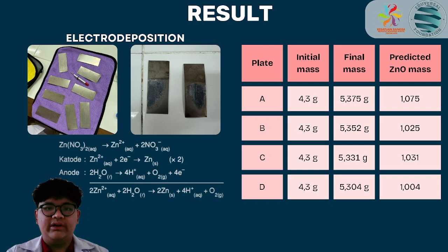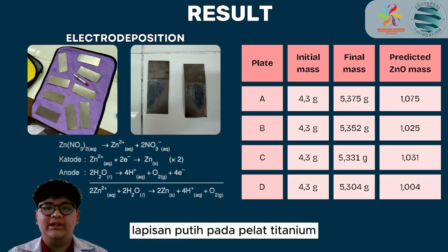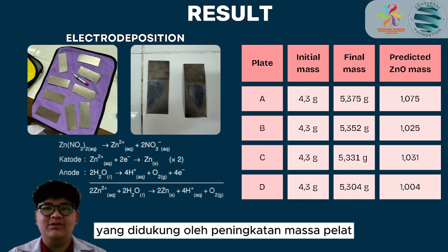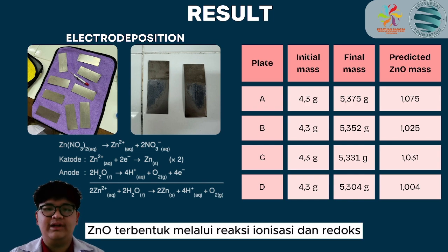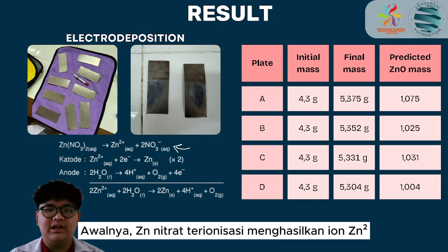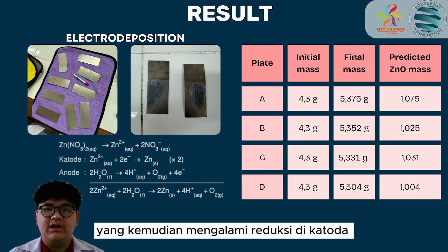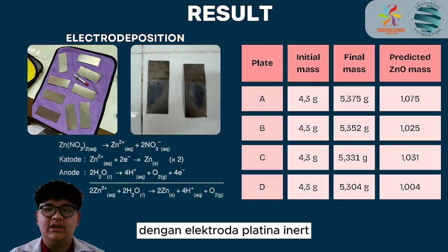Now the result. After electrodeposition, a white layer on the titanium plate indicates zinc oxide formation, supported by the increase in plate mass. Zinc oxide forms via ionization and redox reaction. Initially, zinc nitrate ionized to produce zinc ions, which then undergo reduction at the cathode with an inert platinum electrode, forming solid zinc on the surface. Zinc is subsequently converted to zinc oxide through calcination in a furnace.